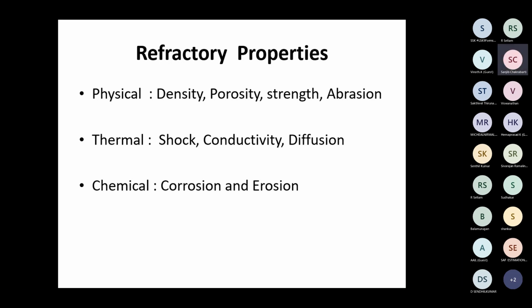Thermal shock and conductivity, diffusion, these are all properties. Thermal shock resistance, conductivity: it has to be less conductive, other than metal refractories. Metal refractories like tungsten and tantalum are conductive. Conductivity is good for metal refractories, but non-metallic ones should be poorly conductive, otherwise heat will be taken away from the furnace. So conductivity has to be low, and diffusion is less. The chemical composition is very important. Out of all properties, the most important are the corrosion and erosion properties.